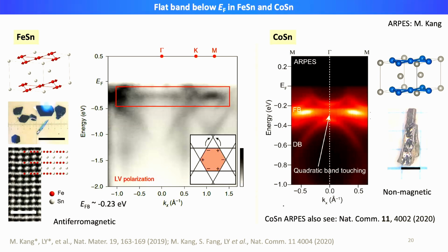Okay. So if we go back to the photoemission spectroscopy of both of these materials, you can see, as a function of the momentum and along the energy axis, flat electronic states across the entire two-dimensional Brillouin zone in both cases. And coincidentally, both of them are located around minus 200 millielectron volts below the Fermi level. So from the photoemission, these characteristic flat electronic states are there.